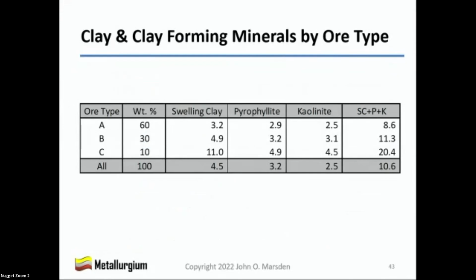He tabulated the three ore types, their weight percentages, and then he did a little bit of a mass balance on the swelling clay, pyrophyllite, and kaolinite. And obviously, ore type C was quite stark in its SC plus P plus K content compared to the other two ore types. So we wanted to superimpose this on the saturated hydraulic conductivity curves.